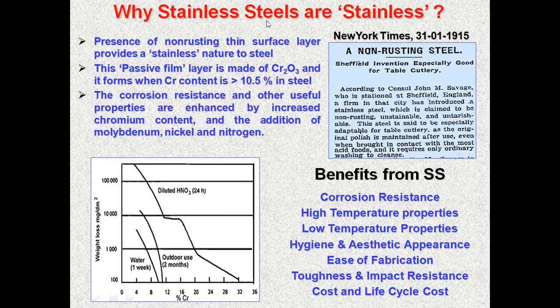This passive film layer is made of chromium oxide, Cr2O3, and it forms when the chromium content is greater than 10.5% in the steel. The stability of the passive film can be enhanced by adding higher chromium content and also addition of molybdenum, nickel and nitrogen. Look at the picture here. As you see the chromium content is increased, you see the corrosion weight loss. For example, in simple water or outdoor use for atmospheric condition, even about 10.5 is enough to give a very low corrosion rate.